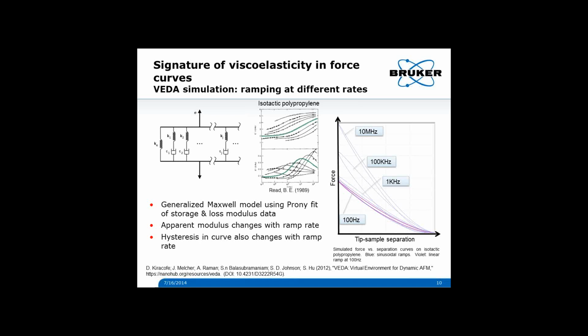The other thing that we see is that there is kind of a larger hysteresis at around 100 kilohertz, and also the 1 kilohertz is actually fairly large hysteresis also. So somewhere in between, say, 100 and 1 is probably a maximum in the amount of hysteresis. That seems to correspond to a maximum in the loss modulus, which kind of makes sense. So basically, we can expect those two things to change if we were to do some experiments and look at things as a function of ramp rate.